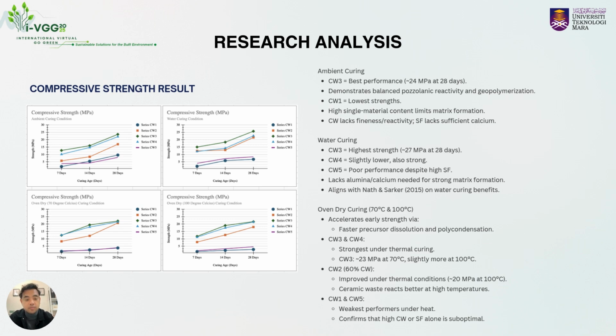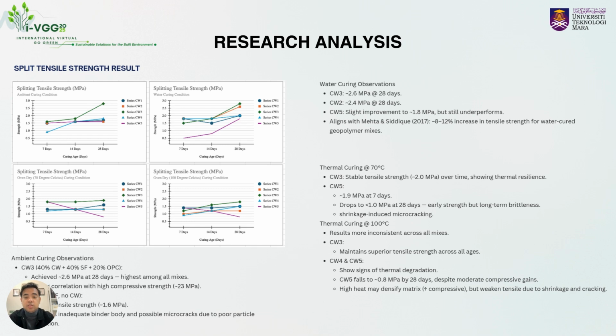integrity. Now let's look at the split tensile strength. In terms of tensile strength, CW3 again outperformed the rest, reaching about 2.6 MPa under both ambient and water curing. This aligns with the compressive strength findings, indicating a robust balanced matrix. Mixes with excessive silica fume, such as specimen series CW5, showed early gains but long term brittleness due to microcracking and poor interlocking.